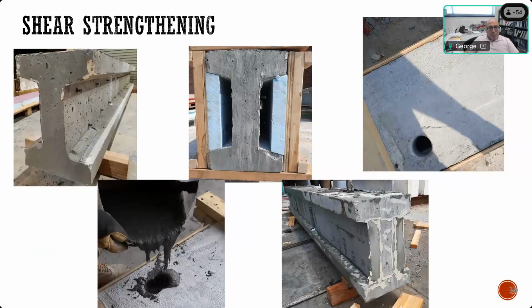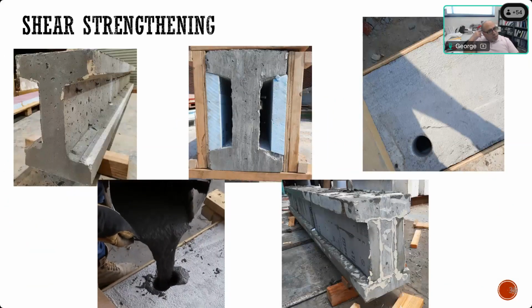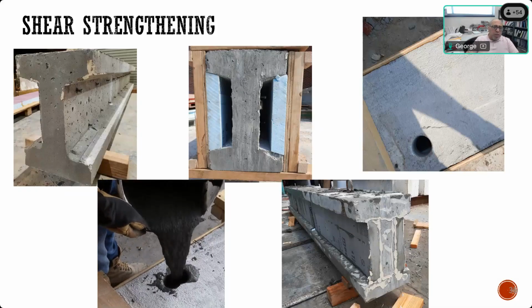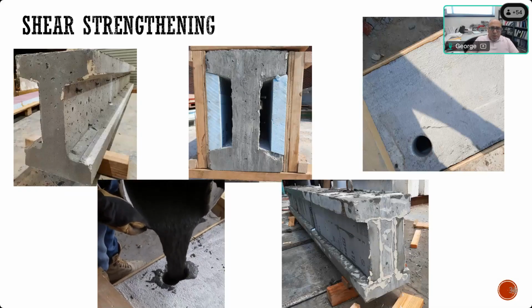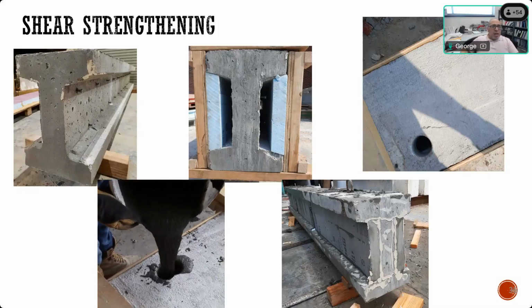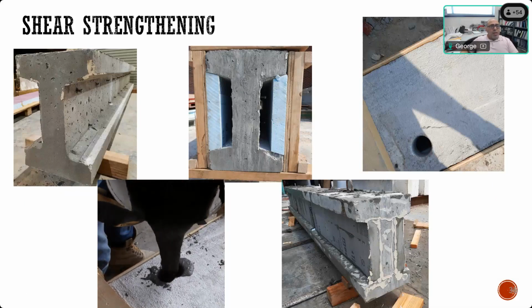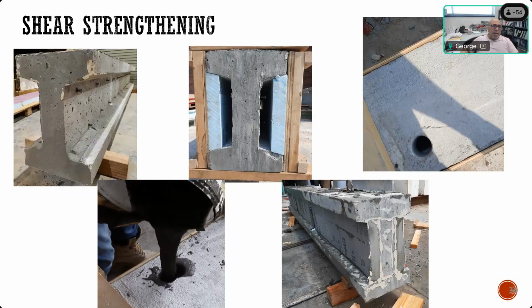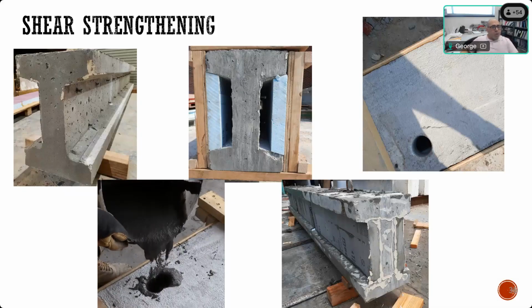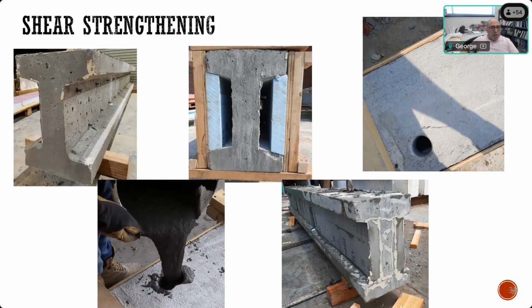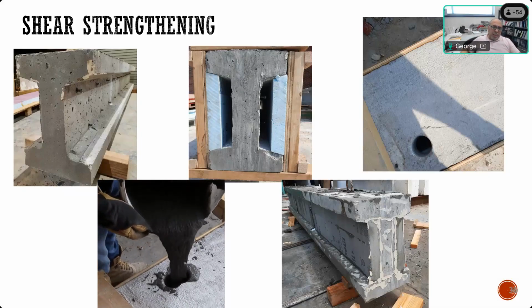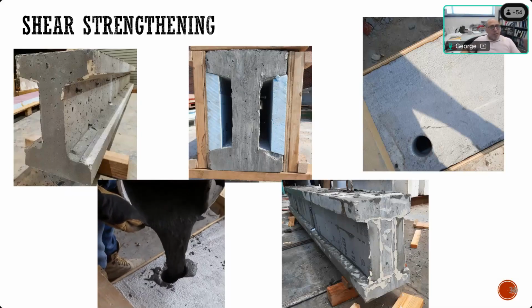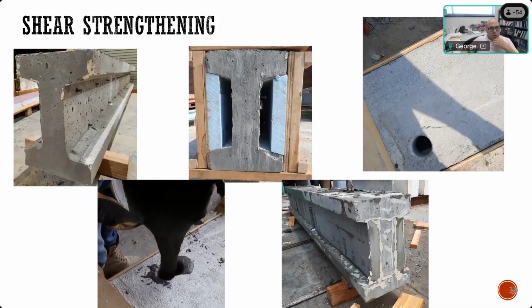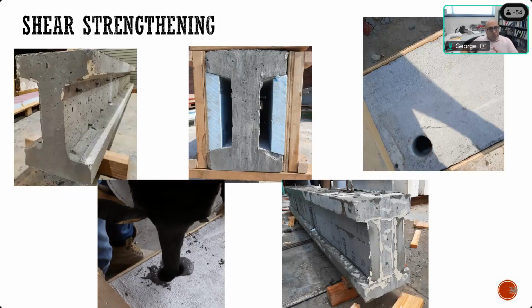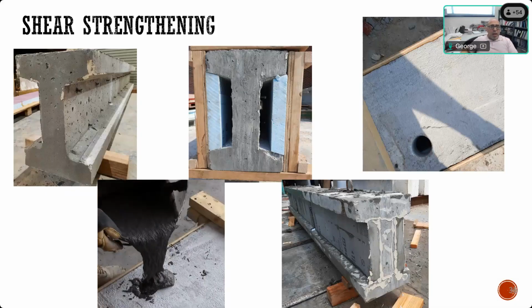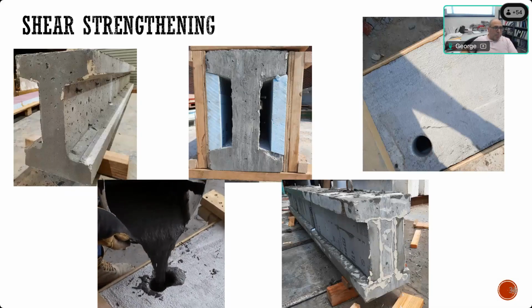These are all actual projects that have a big potential to be successful implementations for UHPC in repair. Within the research project, we looked at different ways of using UHPC to repair, and one of them is trying to strengthen in shear by adding 1.5 inches or 2 inches of UHPC around the web of an I shape. This is, of course, a scaled specimen, not full scale, but it was just to evaluate how much capacity we can get when we cast UHPC around the web.